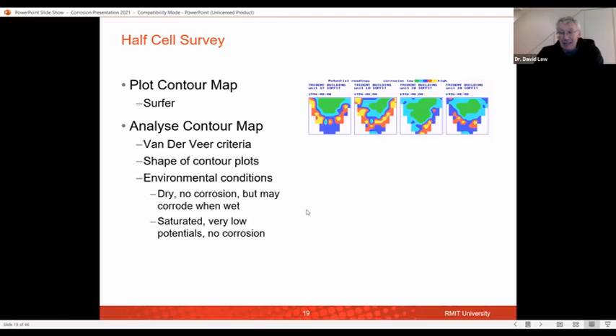In Australia, for example, if you're at the end of summer when it's been very dry, there'll probably be no corrosion because you're in a situation where there's no moisture or little moisture. Equally, if it gets in the monsoon season, there'll probably be no corrosion because there's no oxygen present. So you need to think about, well, what's the environmental condition when I'm taking these readings?